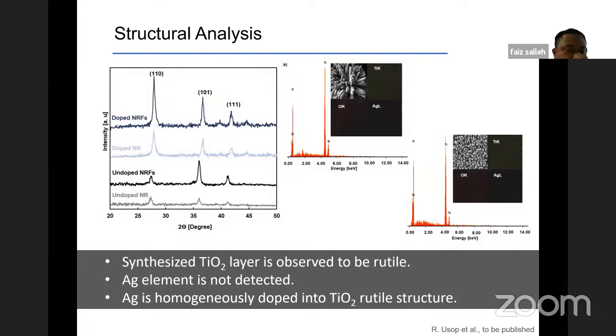So if we look at the XRD and also the EDX results. For example, this graph shows us the XRD result for the doped B layer, doped single layer, and undoped B layer and undoped single layer. We can see that the synthesized doped TiO2 layer is still observed to be rutile, with the respective peaks at 110, 101, and 111. However, if we look carefully inside this XRD, we can see a slight shift of the peak to the higher degree. This is considered to be due to the different size of the silver ion and the titanium ion inside the structure. This will affect the lattice parameter, so that the peaks of 110, 101, and 111 are shifted.